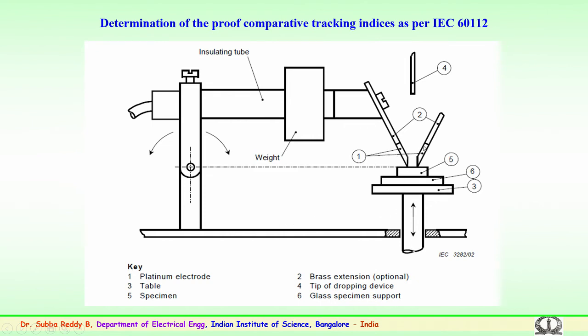Here you have 2 electrodes, where the electrodes are of platinum electrodes with a brass electrode arrangement. Then you have the weight to apply the proper mechanical force which is kept on the sample. This is the sample, the specimen or the silicon rubber which is to be under test, and below that is a glass specimen support for the sample, and this is a small stand.